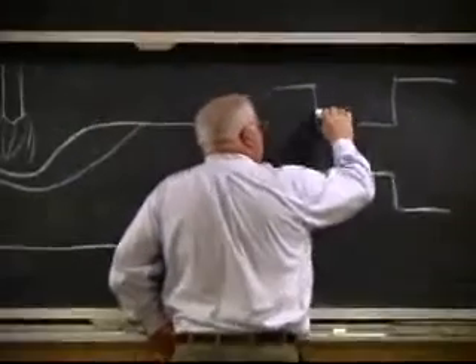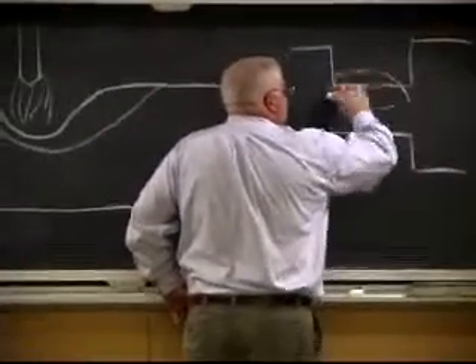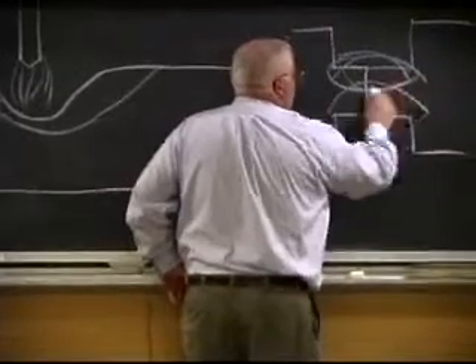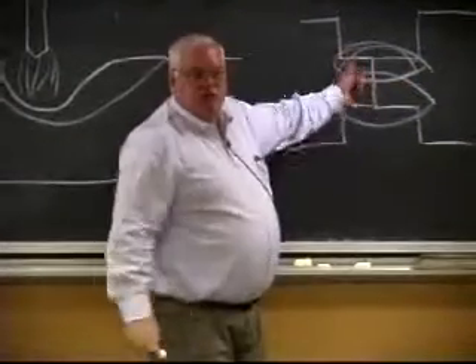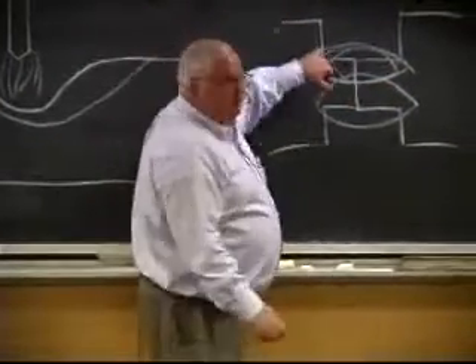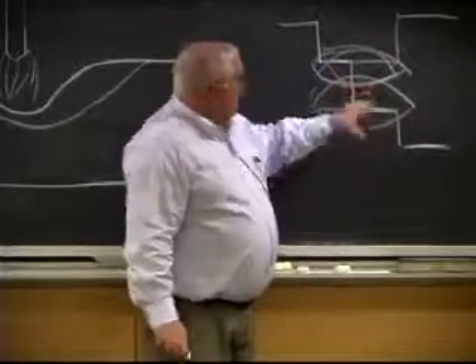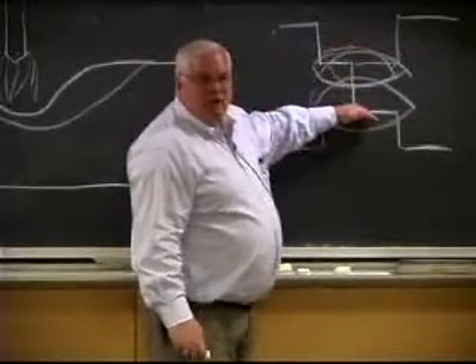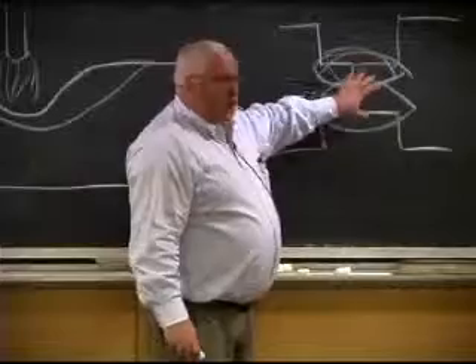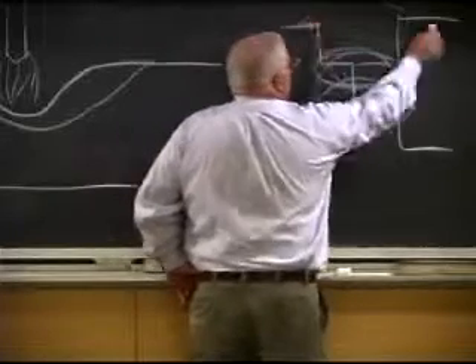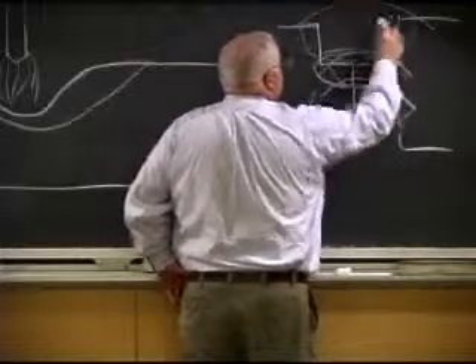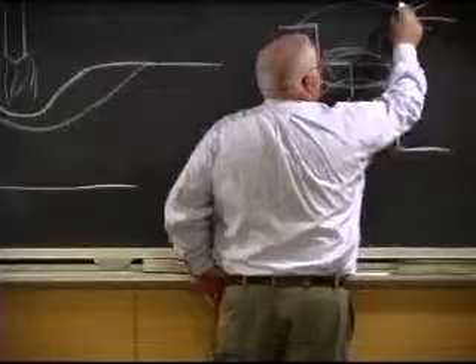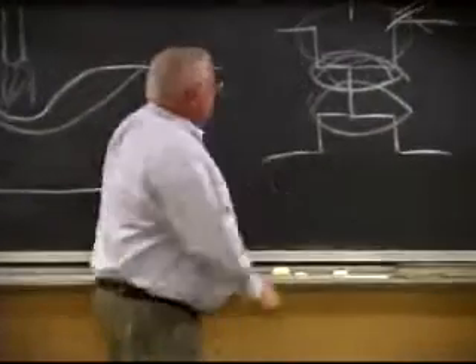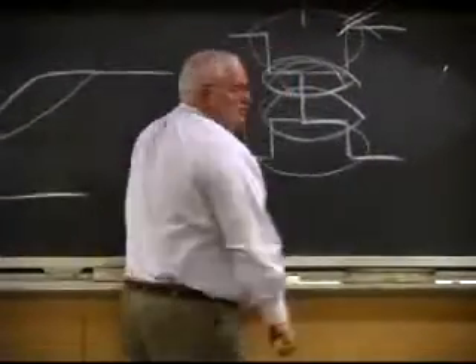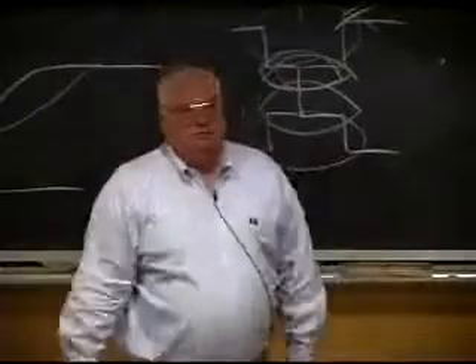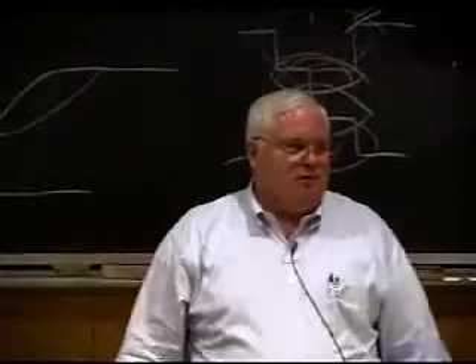They basically would come in here and they could weld a 1/2-inch deep bead in here from both sides by just butting these two things. It was machined with these little lips on them here. So they'd melt one side here, melt the other side here. Great big weld bead. And then they come in up top with a titanium wire feed into this thing. And in 4 passes, they could weld 2-inch thick titanium. Pretty amazing.